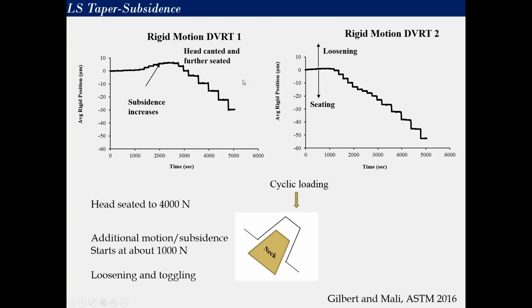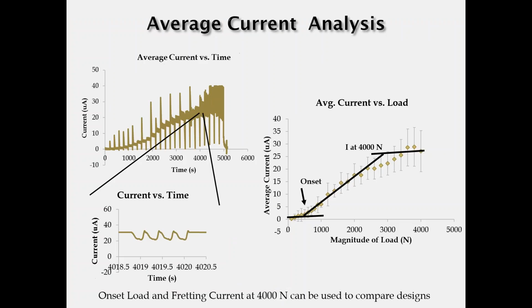So in terms of the head motion, what we see in these relatively short-term, about an hour-and-a-half tests, indicate how the head moves on the neck. And because we have a sensor that's on the superior side and the inferior side, we can get some assessment of the rocking and toggling that might occur. And in this example, for instance, the DVRT1 is a superior sensor, DVRT2 is an inferior sensor about that head-neck junction. And you can see initially the head appears to rotate, that is, rocks upward on the superior side and then seats downward, while the inferior sensor just shows a progressive seating of about 50 microns. And so this is showing you the motion, which is schematically demonstrated in that little cartoon there, driving that implant, the head, into the trunnion.